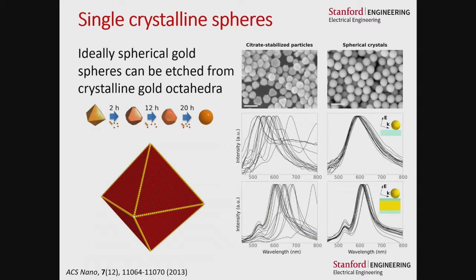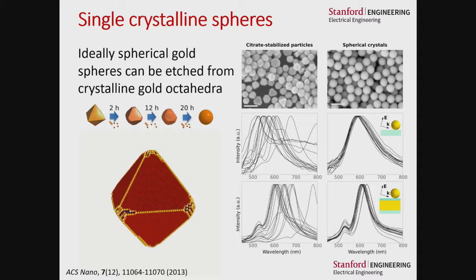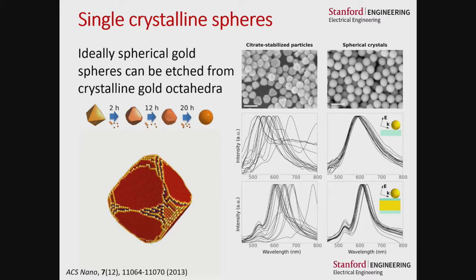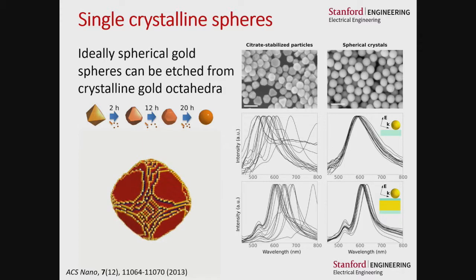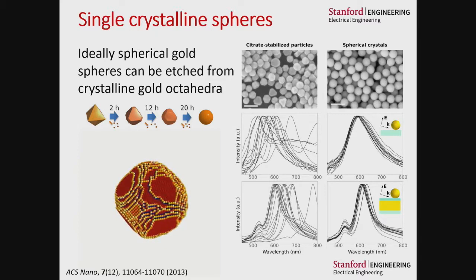Just quickly talking about the colloidal route, this is something that I've spent some time doing. If we want to make really ultra high quality single crystal gold spheres, there is a route to do this. We can start with single crystal gold octahedra and slowly etch them in chloroauric acid until they become spheres. We can see through this kinetic Monte Carlo simulation that this works because the etching typically attacks the edges and points on these octahedra, which allows it to smoothen and give us spheres.